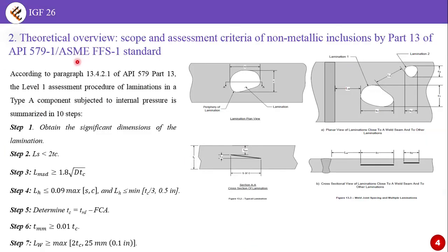Part 2, theoretical overview. Non-metallic inclusions are not considered a defect by code standards. These standards consider them as a lamination for assessment purposes of structural integrity. In this case, according to paragraph 13.4.2.1 of API Part 13, the level 1 assessment procedure of lamination in a type A component subjected to internal pressure is summarized in 10 steps.